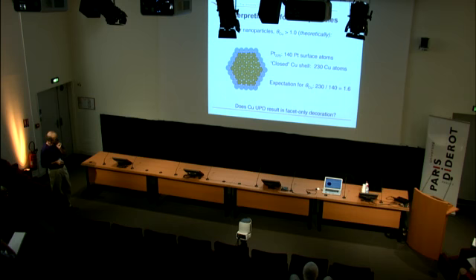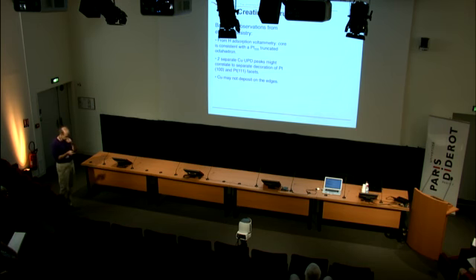And so the question was, why is this? This is a case, by the way, where you get the result that you're expecting, and you're very excited. Of course, it's the boring result. So why do you get so excited, right? And now you get something that you don't expect, and now that's actually much, much more exciting because now you have to figure it out. And so the first thing we thought was, are there unique sites on these nanoparticles where copper deposits? And the likely sites are the facets. And so we developed a model that we thought might account for this observation.